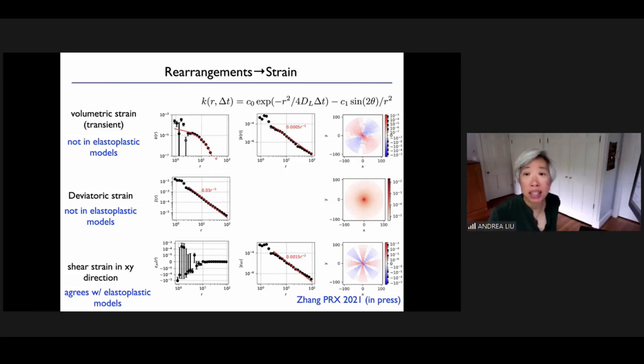And the transient piece is isotropic, so it survives when I take the angle average, but it is transient. Okay, then there is a deviatoric strain. This piece is actually not usually included in elastoplasticity models, which decays like 1 over r squared and is isotropic. And this comes from the fact that I can trigger what this, well, hold on, I will say that for later.